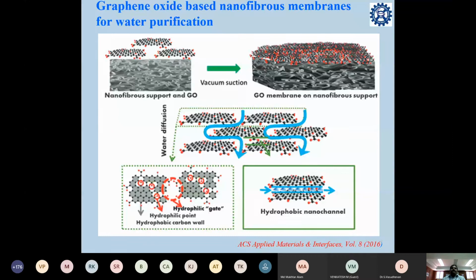Okay, so here we can see this graphene-based monolayer or graphene-based layers are coated on the nanofibrous support. So here the nanofibrous support is used to coat the membrane on the top. So what we can see in the slide here, the graphene is coated on the surface, and then it undergoes vacuum suction to make GO coated. That means GO in the sense graphene oxide. So this GO is coated on the nanofibrous support.